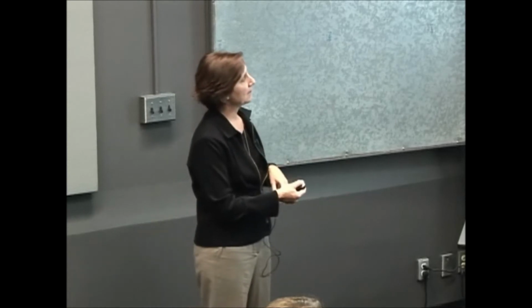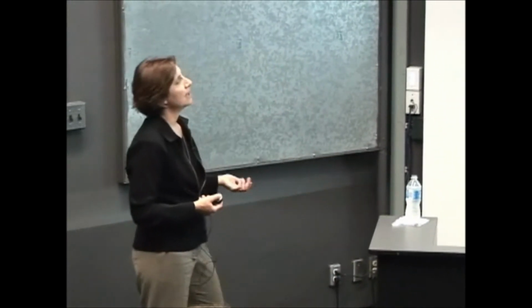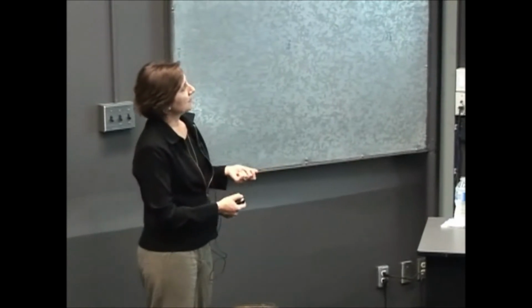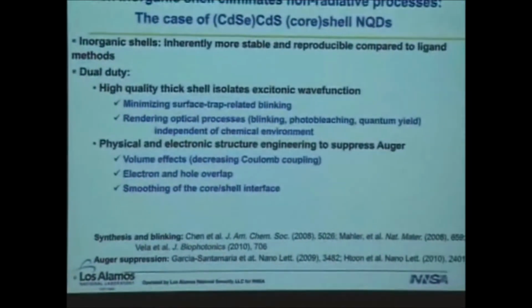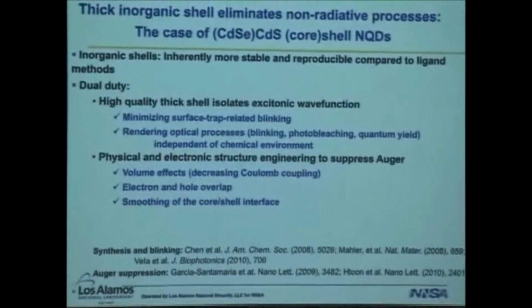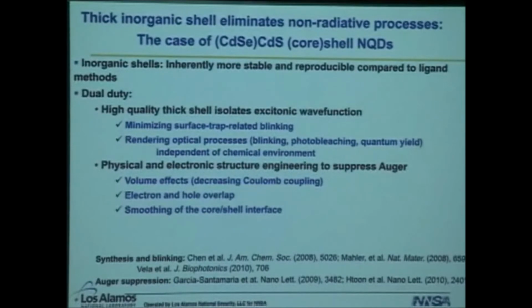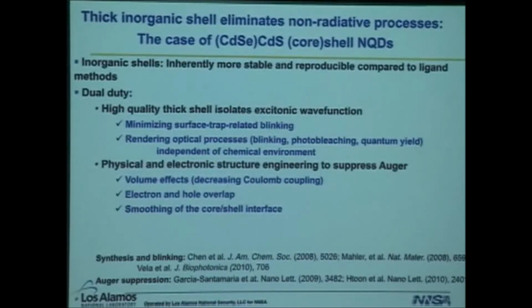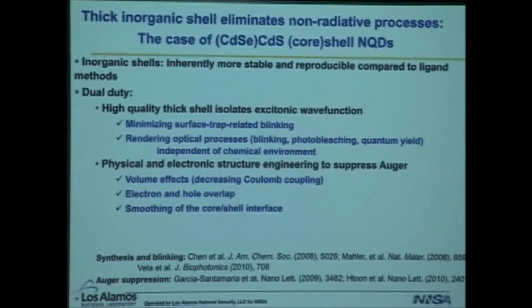Number one, we thought that if you created a very, very thick shell, you could effectively isolate the excitonic wave function that you generate under optical excitation, for example, and therefore minimize any surface or surface trap related behavior. In addition, it would render optical processes such as blinking or even photobleaching, and the ensemble level property of quantum yield, independent of the chemical environment of the quantum dot.